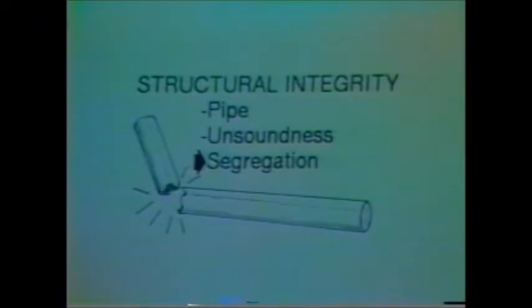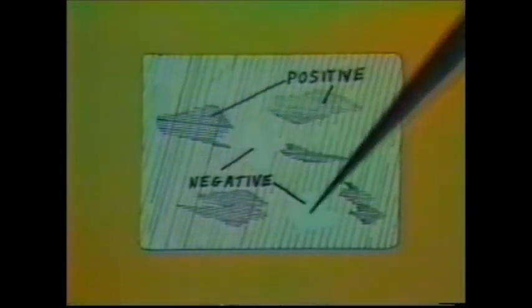One other type of internal integrity characteristic is segregation. When steel solidifies, it tends to attract mostly iron atoms to the grain structures that form. This forces other elements to remain in the molten portion, concentrating them in the areas that solidify last. Slower cooling rates give non-metallic elements more time to migrate, resulting in areas that are much higher in concentration of these elements, positive segregation, or lower, negative segregation. Temperature effects like convection currents and gas bubble formation provide many areas for segregation. Thus, killing a steel, that is, adding a chemical to absorb the gas bubbles, can often lower the levels of segregation. The detection of segregation involves a hot acid etching process to speed up the different rates of surface etching, followed by microscopic examination of the etched surface.